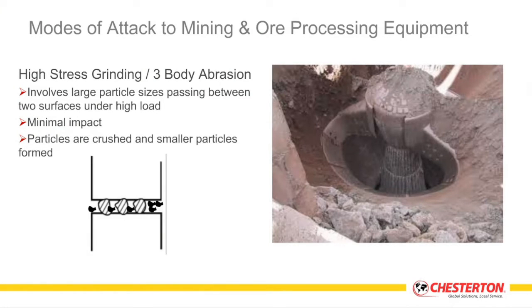The next area where you see severity is the high-stress grinding abrasion. This is also sometimes categorized as three-body abrasion. This oftentimes will involve particle size reduction passing between two surfaces under high load. So you may see this also in crushers, but you will see this more commonly in the grinding or milling phases. These could be hammer mills, these could be rod mills, these could be